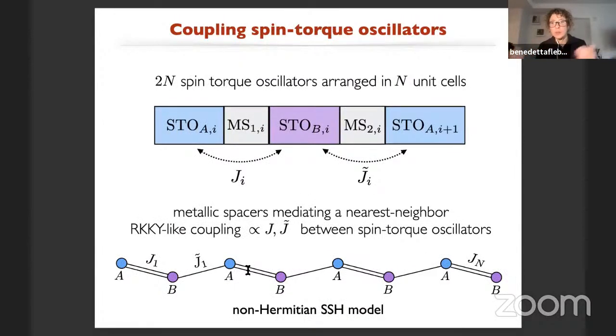Now we decided to couple them. As theorists, we couple them in a very imaginative way. So probably this is going to be a bit tougher to do, obviously from the experimental side. But we imagine that there are metallic spacers, or maybe a common metallic spacer, connecting different spin torque oscillators. And I'm labeling 1A and 1B because I want to create a unit cell that contains two of them. Why? Because I want to modulate the RKKY-like coupling between two different spin torque oscillators. So here we have this exchange-like coupling with a certain strength, but this one will have a different strength.